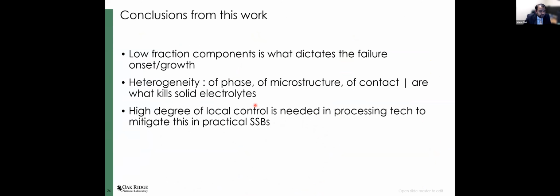And so wrapping up, what I wanted to say was, using this high energy diffraction microscopy for the first time with solid electrolytes, we're able to show that these low fraction components are what dictate failures, its onset and its growth in solid electrolytes. The heterogeneity, be it of phase, be it of microstructure, be it of contacts, is what kills solid electrolytes. And we also determine using this information that we need a high degree of local control in order to process these solid electrolytes and mitigate these failure mechanisms when we move to practical solid state batteries.